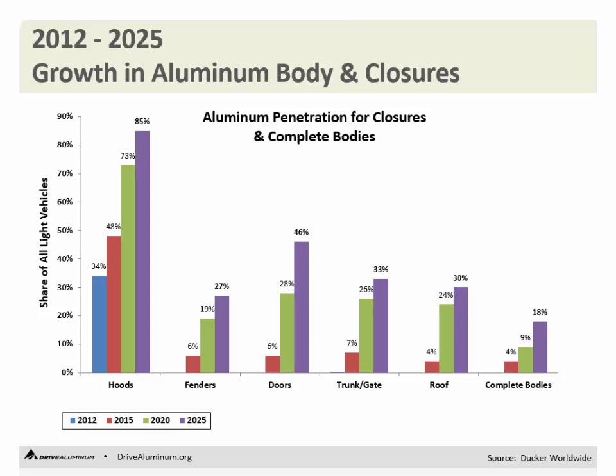Again, if we look at it by individual componentry, we can see that hoods are the single largest growth area, going from 35% of the market today to about 85% of the market by 2025. The next largest area is doors, which are a fairly low volume, low penetration today, and with the Ford truck will move up to about 6%. Will grow to almost half the market in doors by 2025. And overall, in complete body structures, this is the F-150 in 2015, growing to about 18% by 2025.